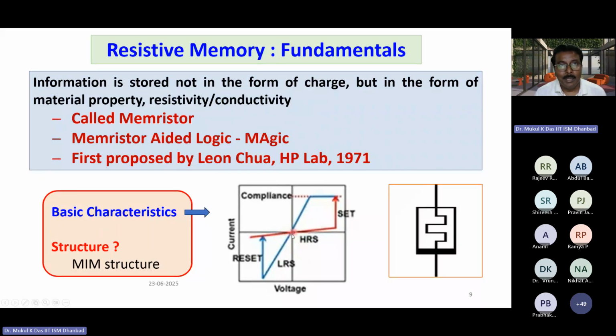And similarly, if we interchange the polarity of the voltage across the resistor, that is on the negative side, current initially, you see, is very low in a red line, and suddenly it increases to a very high value, and again when we trace back to 0, it reduces to 0 current, but through a different path. That means we can observe here it is unlike an ohmic behavior, a particular resistance which behaves like a variable resistance. For a particular range of voltage, it gives a low resistance. For another region of voltage, it gives a high resistance. So this is called the variable resistance, and this is also the building block of a memristor. And the symbol of this memristor, people have decided to represent in this way.